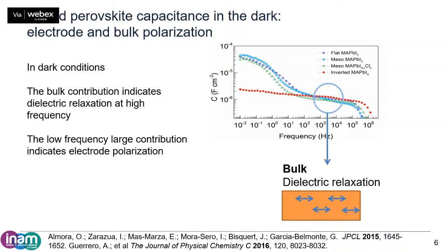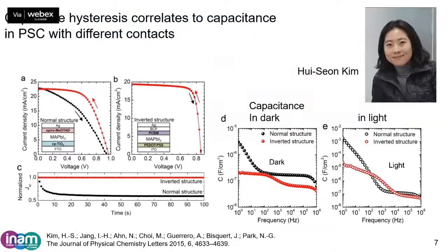of the perovskite with the dielectric constant of 25. This is normally called the geometric capacitance. But when you go to lower frequency, you have another very big polarization. It's quite high. This is universally observed, but sometimes it can be suppressed, especially for organic contacts. And this is now attributed to surface contact phenomena related to the ionic double layer.